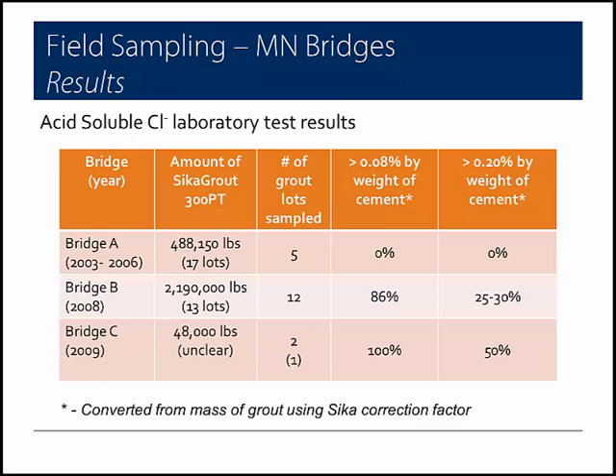In terms of the lab testing, as mentioned, we collected a number of samples and they were submitted for acid-soluble chloride content testing. Bridge A, which has approximately 500,000 pounds of SikaGrout 300PT in it, consisting of 17 different lots. 5 of those grout lots were targeted for sampling, and in all cases, the chloride content was less than the PTI specified limit of 0.08% by weight of cement.